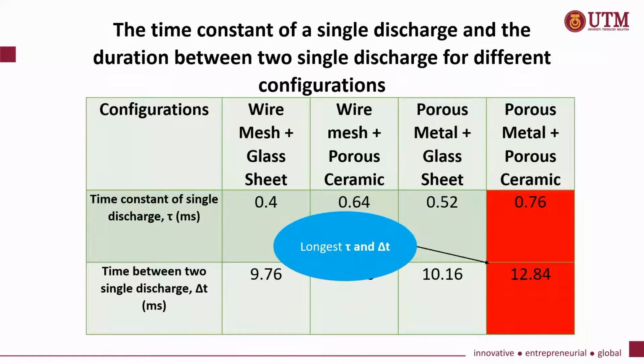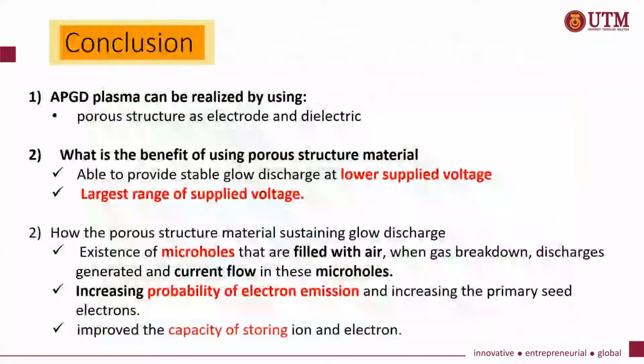This tabulated data also shows that the configuration which uses the porous structure material helps in sustaining the single discharge for a longer period, since the time constant for this configuration is the largest. In summary, we can say that the glow discharge produced by the configuration with porous metal as electrode and porous ceramic as dielectric is the best configuration compared to the others, because it is able to provide stable glow discharge plasma at a low supplied voltage and for a larger range before changing into mixed glow filamentary discharge.